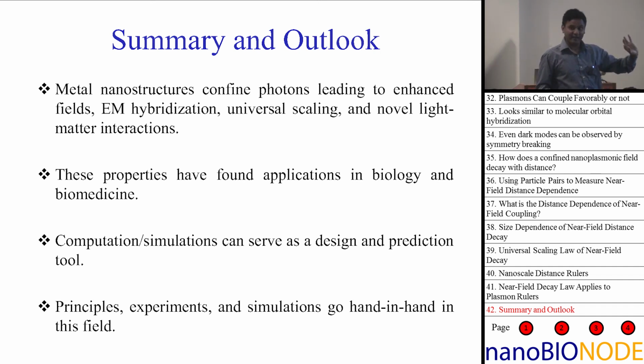It is S divided by D, meaning the distance relative to the size of the particle. If you double the size of the particle, the distance scale of this ruler doubles. So it's a scale. You can scale the problem up, and the physics stays the same. That's for two particles, a one-dimensional system.